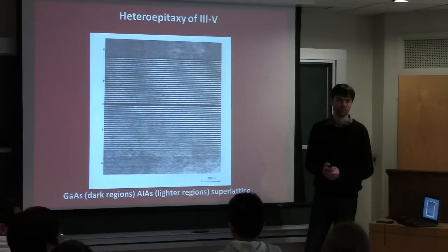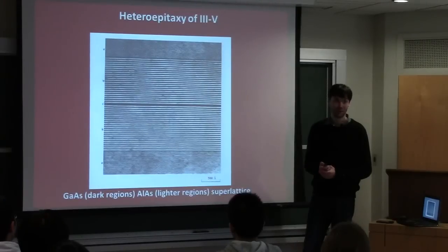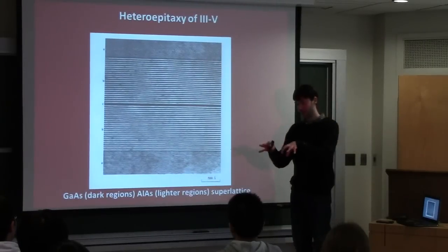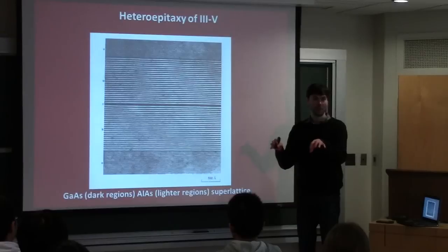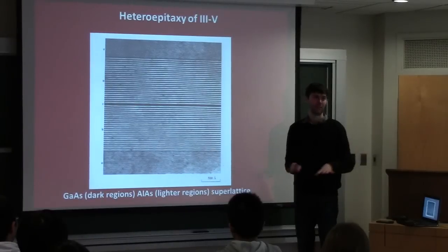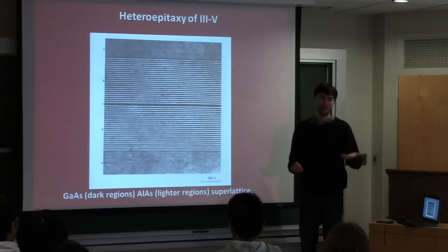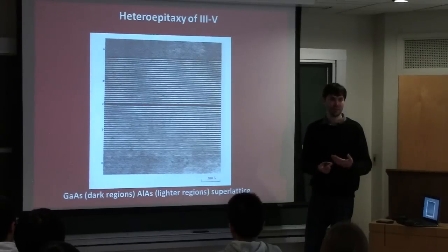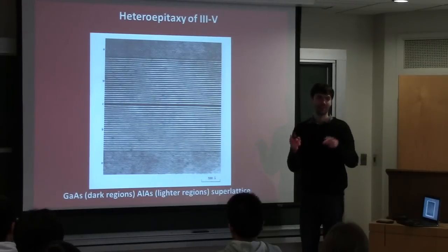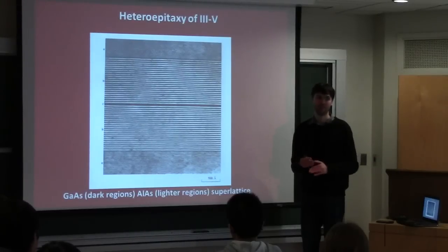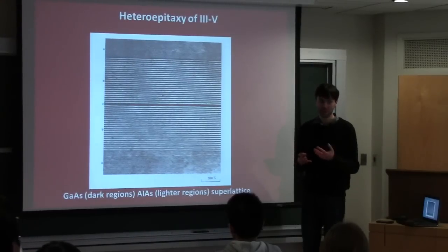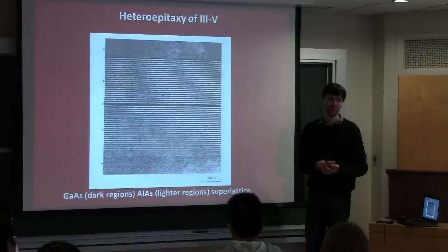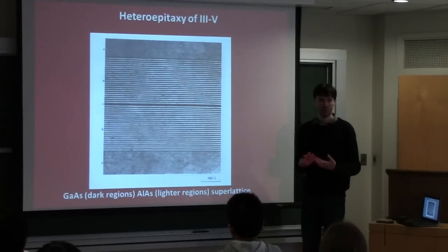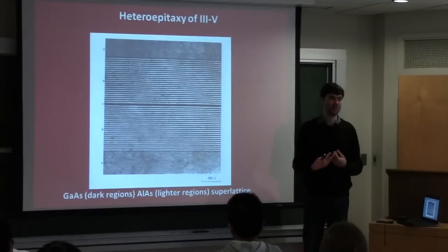In real time, how do they account for the fact that the layers probably aren't going to grow evenly? They do grow evenly. First they cluster, and then finally they form a perfect layer. Okay. And that is the art of MBE. So that is the epitaxy in MBE, growing layer by layer. So they tweak the growth parameters such that that is true. Okay. And they study the dynamics of how atoms diffuse on the surfaces versus the influx of atoms.